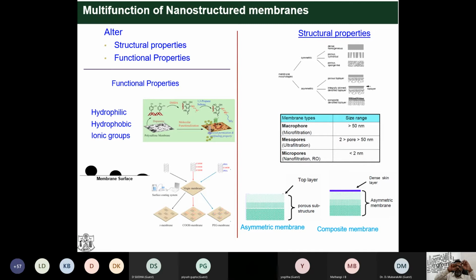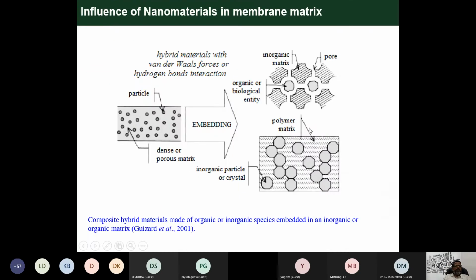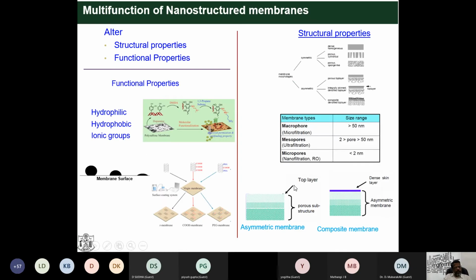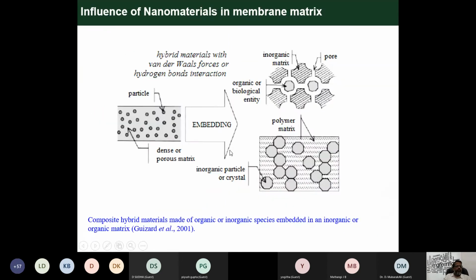The thickness is very small, so it is very difficult to travel because this is a skin layer. There are no big pores; anyway, they have pores, but the pores are very few. So they travel from this point to this point very slowly. Once they reach here, the remaining part is pores, and they move very fast. That's the reason we develop this membrane with an asymmetric structure. Here, the structural and functional properties play the main role in transport.